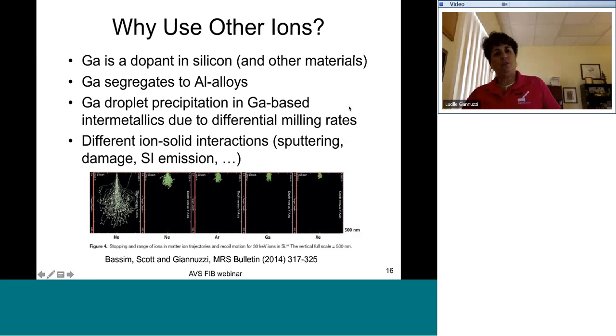So why might we use other ions, however? Gallium can yield detrimental results to certain materials. First of all, it's a dopant in silicon and some other materials. It segregates to aluminum alloys. You can actually get gallium droplet precipitation in gallium-based intermetallics due to differences in milling rates. And in some cases, you might want to just generate different ion-solid interactions. That is, get different types of sputtering behavior, different kinds of secondary ion emission, for example, through doing SIMS analysis, etc. So if we take a look at this, this is a SRIM calculation.